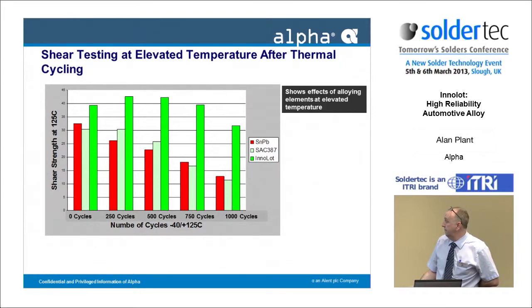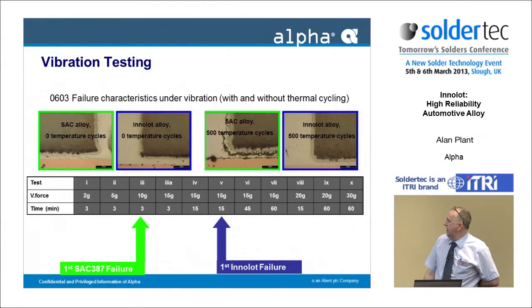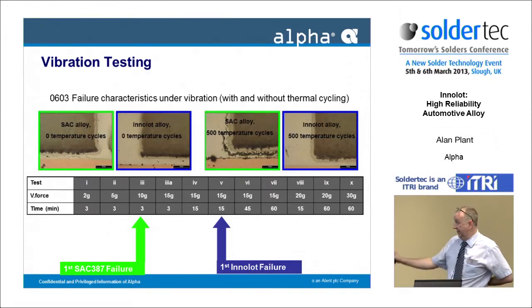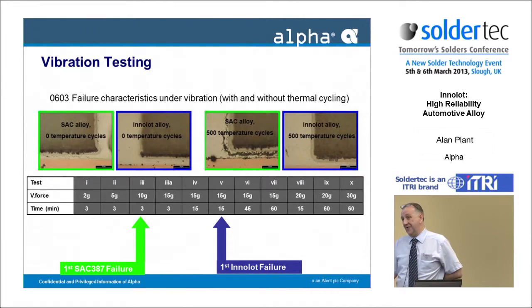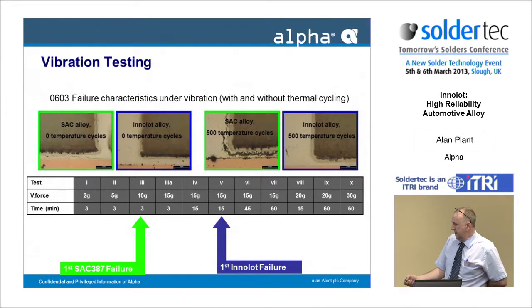particles. Okay. And then finally vibration testing, and we had a discussion earlier on about whether the vibration test is done as thermal cycling and then vibration, or done at the same time. But this is just a snapshot of the data. We're basically finding that both the force and the time, the duration of the vibration for the SAC, is a lot less than with Innolot.